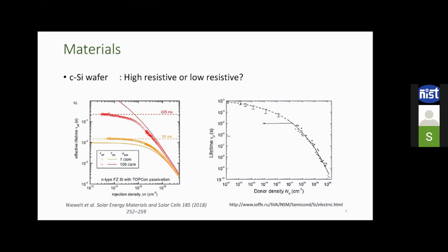I would say this is quite intuitive, because doping is, after all, a process of incorporating impurities inside your material. The higher the doping density, the higher would be the defects inside your material. The presence of such a high density of foreign atoms increases the defect density, and then there is a fair amount of chance that your photogenerated minority carriers will recombine within these defects, and therefore their lifetime will be less.